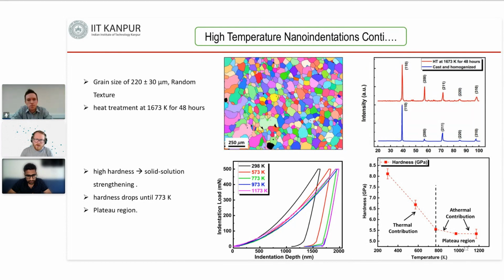A further question from Dr. Nath, who asks, what is the accuracy of simulation compared to actual results? I guess the deviation from the experimental is a little bit high, I will say, if it is not one-to-one matching, because with ab initio MD you need to find the exact correlation function, and even with the experimental testing, we are indenting very small material, so there is an anisotropy effect. So the variation is large, but we can say the variation is because of the material property, the anisotropy and other things, and the simulation also. Okay, thank you.